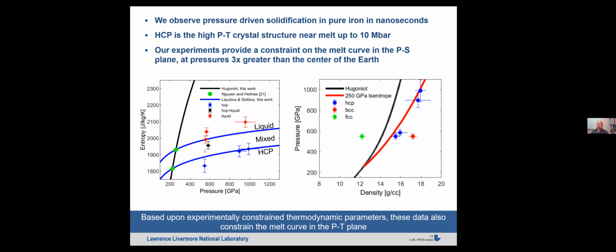So you're also referring to the fact that shockless compression, so a shock will add entropy, but shockless compression also adds entropy because in a solid, there's plastic work heating done by the strength, deviatoric stresses of the material, and in a liquid, there's viscosity. However, for all but one of these experiments, most of the compression was done in the liquid state. And for our assumed and calculated viscosities of liquid iron, the amount of heating in temperature space is a few to tens of degrees.